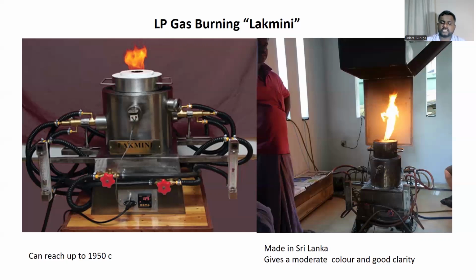From this machine you can achieve a moderate level of color, not as good as the Thai condor machine, but we can get a nice luster from the Lakmini furnace because it can reach heats up to 1950, and we can more or less fully remove the inclusions, rutile needles, from the stones. So we can create a nice stone without any inclusions or rutile needles. But compared to the condor machine, the environment in which the gems get burned is not so reducing. It does not give a very vivid, vibrant blue color.